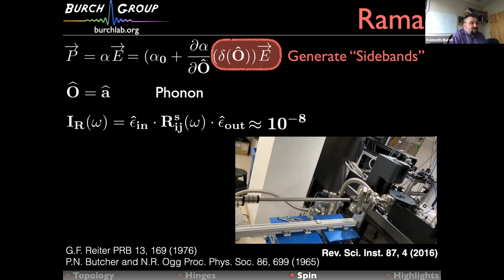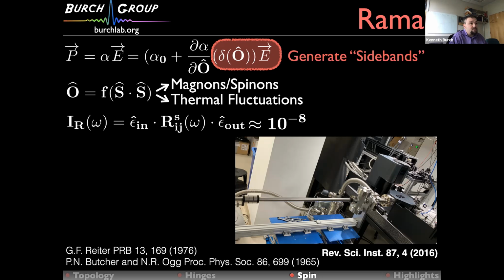In any event, we've built up a custom system where we can vacuum suitcase. And this gets back to Doug's question earlier. We can vacuum suitcase from our glove box into our low T Raman, which can, by the way, also do transport and photocurrent. So if you have air sensitive materials, we can help in another way. Now, if you have spin orbit coupling, then the operator that couples to your polarizability could be some form of S dot S, in which case the noise that you're seeing could be magnons or spinons, and that's actually how we see them in Raman. It can also just be the standard thermal fluctuations of your magnetism.